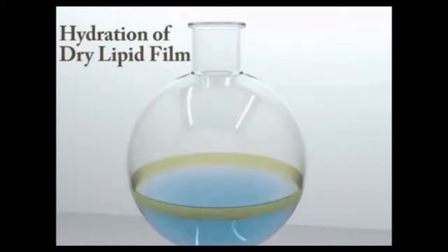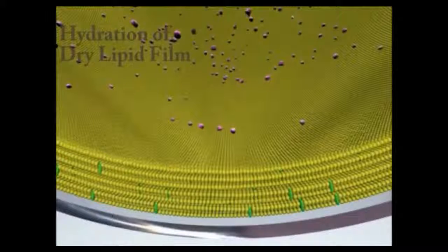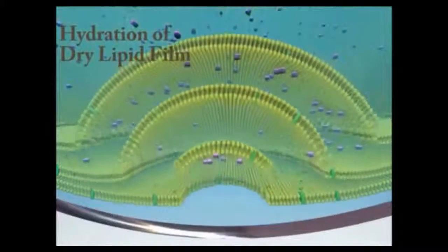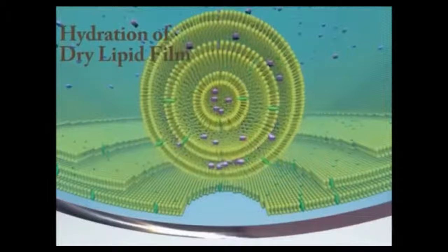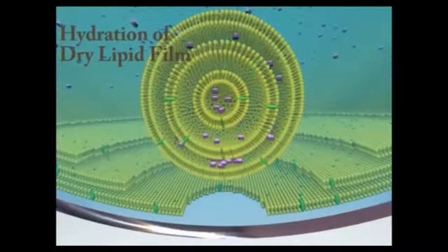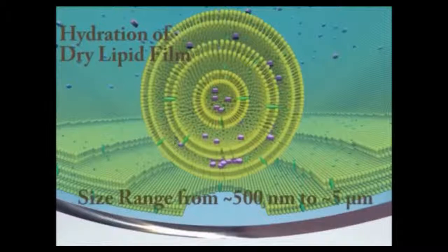The aqueous solution must be heated above the phase transition temperature of the lipids in order for the liposomes to form. The resulting multilamellar liposomes consist of many concentric lipid bilayers, while all or most of the lipid-soluble compounds will be incorporated into the bilayers of these liposomes. The amount of water-soluble compounds entrapped is usually very low because the MLVs have a small captured volume. Very little aqueous solute penetrates the onion-like layers of hydrated lipid bilayers.